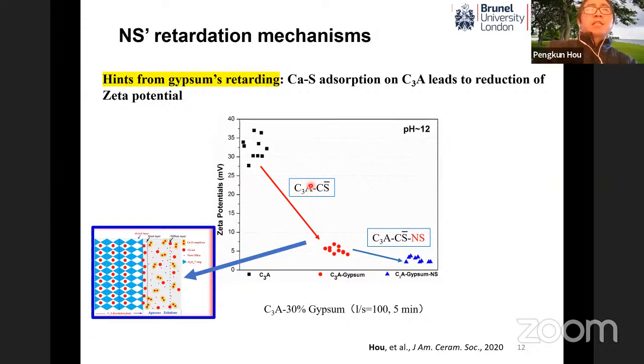Regarding the mechanisms, actually we can get some hints from the effect of gypsum on the retarding of C3A. So when the gypsum was added into the C3A system, I think it is recently confirmed that the calcium and sulfate form a complex, which can be adsorbed onto the positively charged C3A particle surface. And this kind of adsorption will lead to the reduction of the potential of the C3A particles, and also blocks the dissolution of the C3A particle, which will finally reduce the hydration of the C3A.